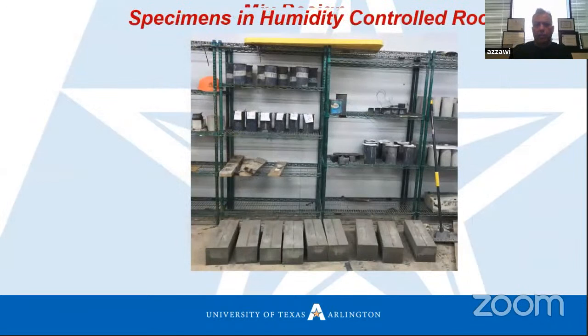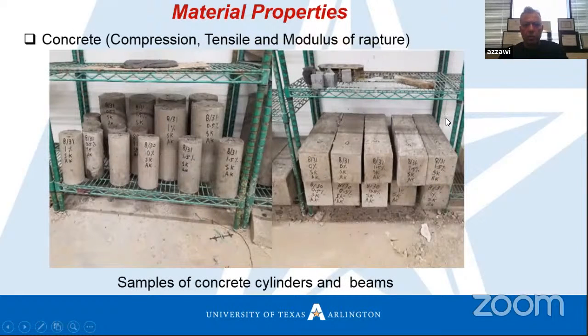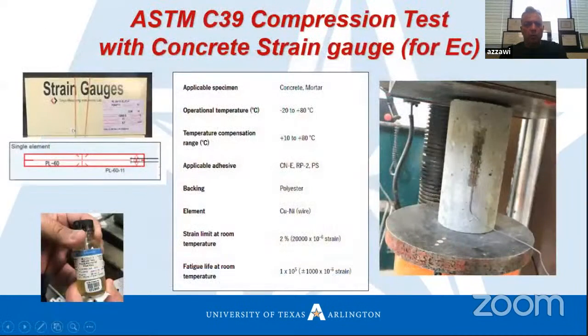After preparing our specimens, we put them in the control room. In our lab at UTA, I prepared samples for the flexural test, compressive cylinders for the compression test, and cylinders for the split tensile test. These are the samples. This is for the flexural test, this is for the compressive test, and this is for the split tensile test. After 28 days, we start testing.